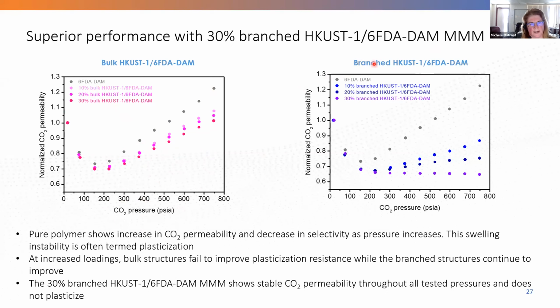Whereas when you look at the branched MOF materials, with an increased loading to 10%, 20%, and 30%, you actually see a complete elimination of the plasticization. So these materials, particularly at the 30% branched MOF content, show very stable CO2 permeability throughout the tested pressures. And you also see that it doesn't plasticize.